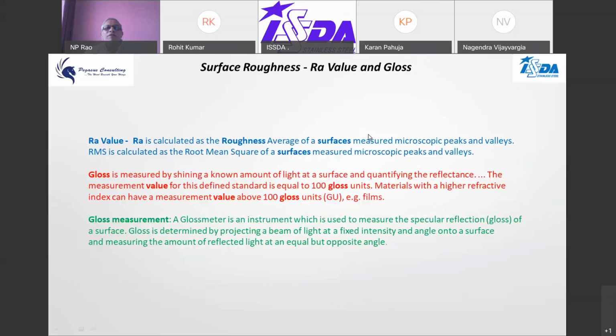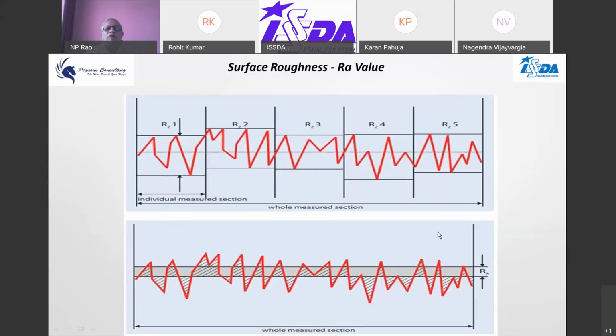Coming to surface roughness and gloss. Now, surface roughness is a very important parameter in terms of the surface finish of stainless steel, where you can use a surface roughness instrument to measure the microscopic peaks and valleys of the surface of the material. Once again, gloss is a term used to check the reflectivity of the material surface, and you can use a gloss meter to see how much reflectivity or shine or gloss is there on the surface of the material. This is a typical measurement of roughness, an Ra value, peaks and valleys, and these can be obtained by using measurements.